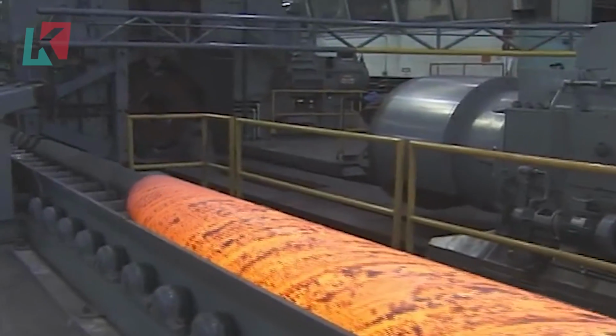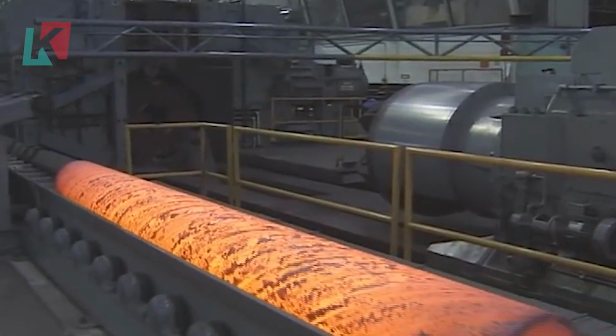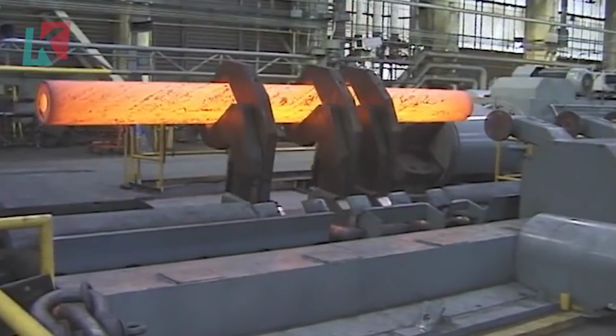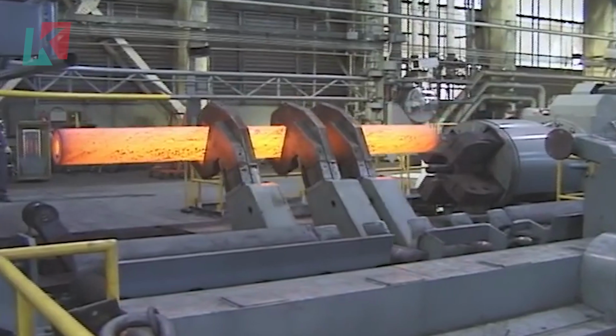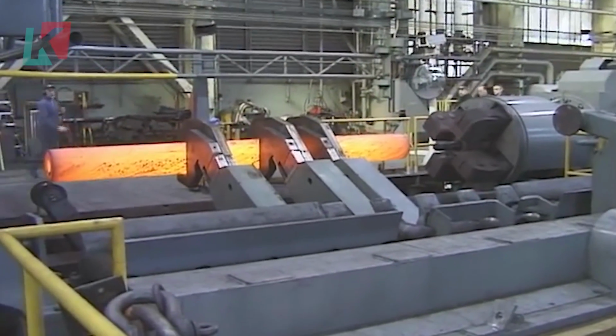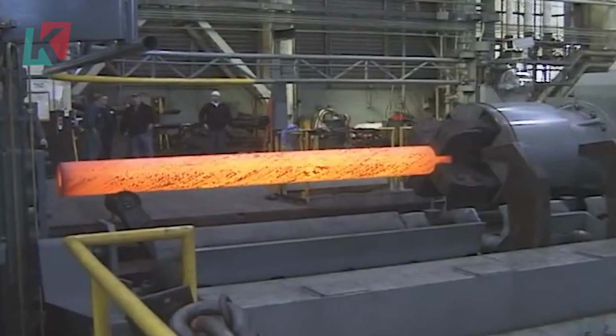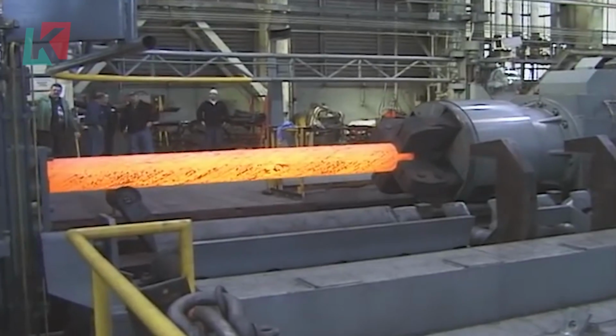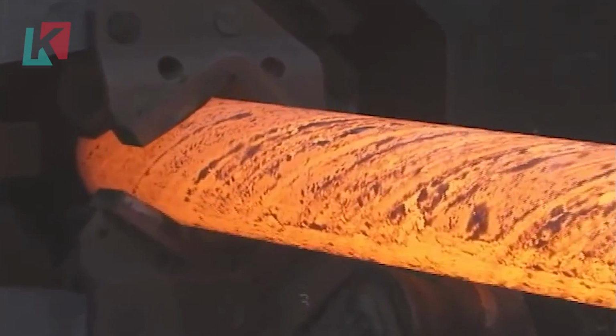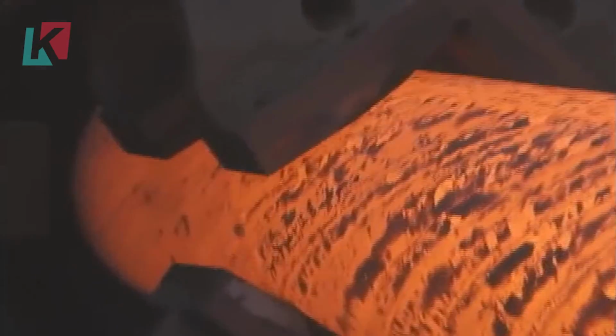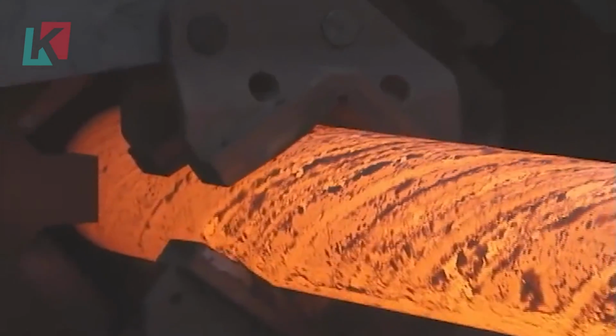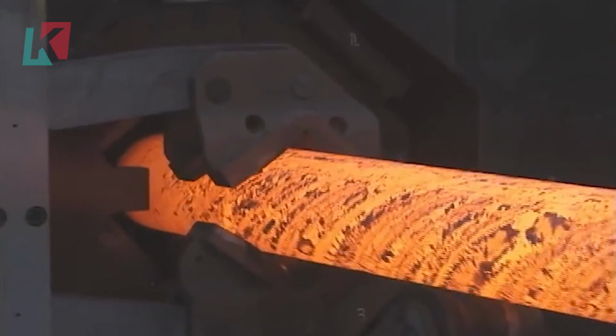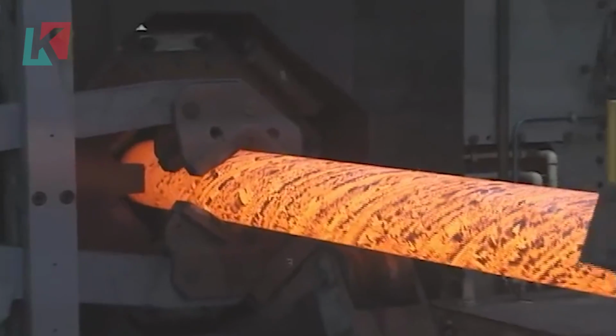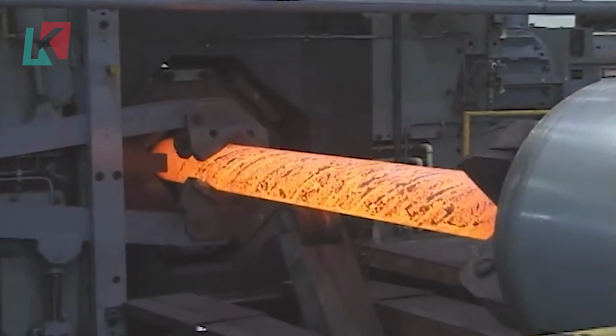It's engineered to withstand pressures exceeding 60,000 psi and temperatures over 3,000 degrees Fahrenheit when firing. The heart of this operation is the rotary forging machine, a technological marvel that can apply up to 3,000 tons of force while rotating the workpiece. The billet is heated to 2,100 degrees Fahrenheit in a carefully controlled atmosphere furnace to prevent oxidation. Temperature uniformity is critical. Variations of even 50 degrees can create stress concentrations that could lead to catastrophic failure.